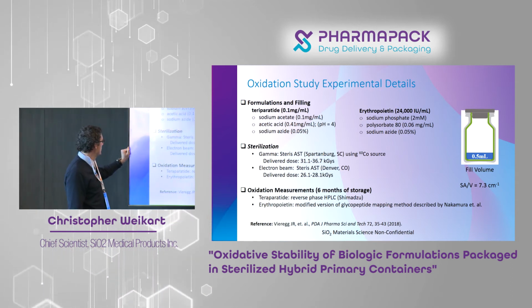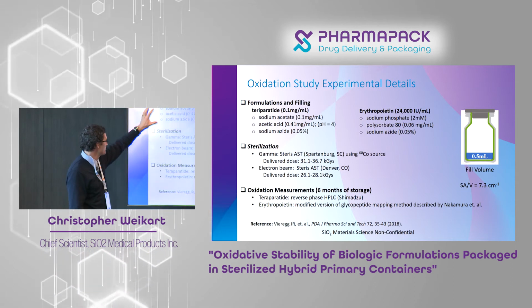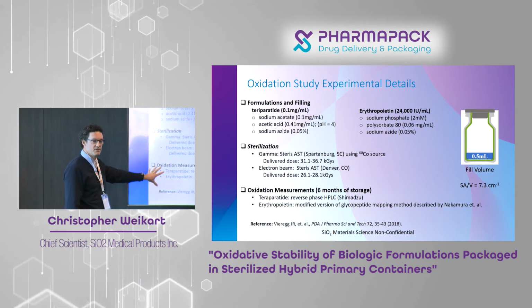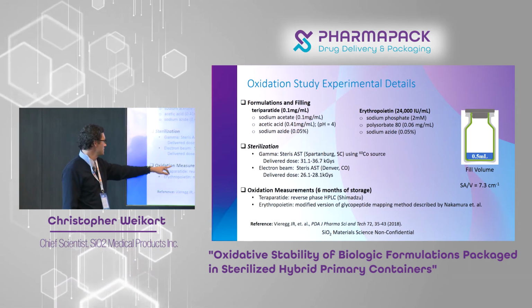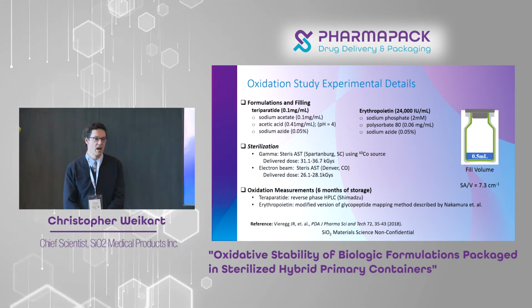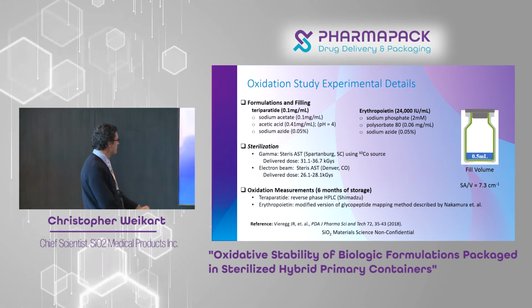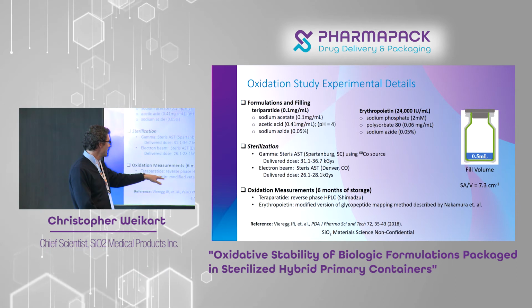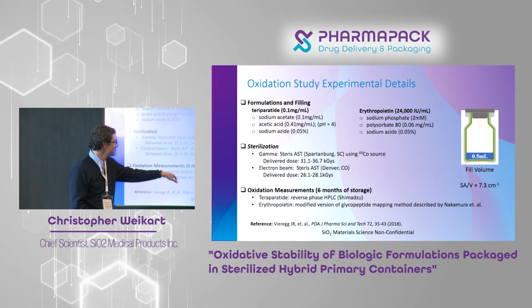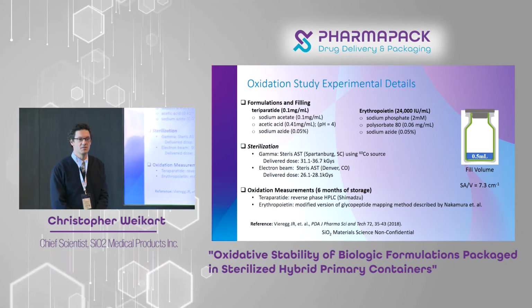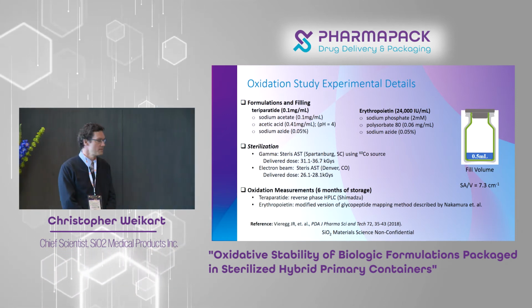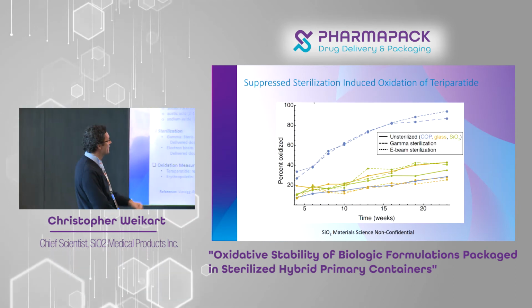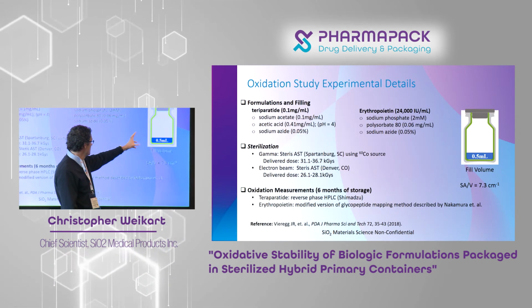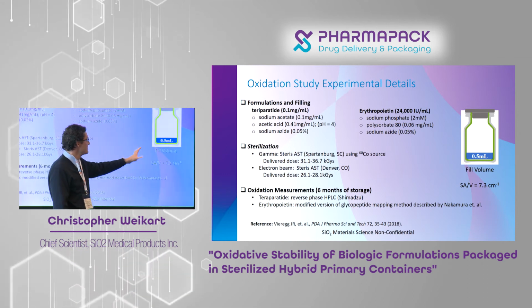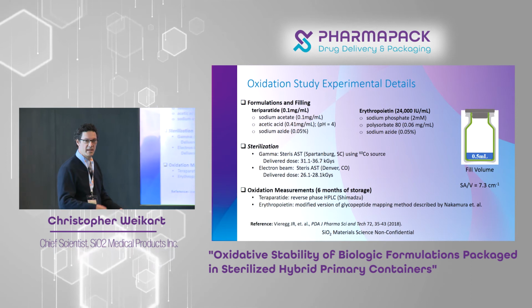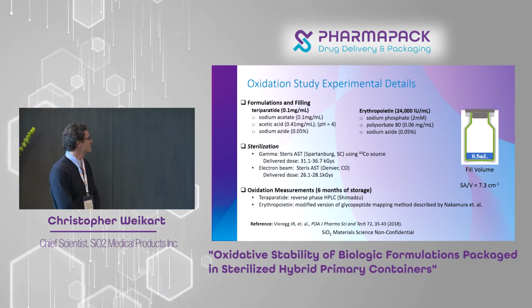And then, of course, we've already sterilized the container. We put the drug in it. And then we ran these oxidative measurements. One for teriparatide using reverse phase high-performance liquid chromatography, which is a pretty standard method. And then for the erythropoietin, since Nakamura had used this same drug, we basically mirrored the exact same analytical technique he used to look at oxidation of that drug. One other thing is, in this case, we're using vials, so the surface area to volume ratio, we tried to mimic that of a syringe. We are duplicating these results in syringes, but just to mirror that for a syringe.